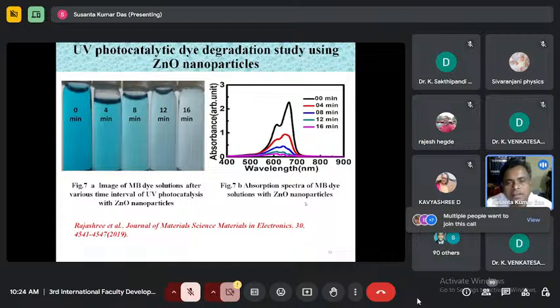Then we had gone for the results that we have shown here. You can see these are results of photocatalysis of MB dye. When we go for the experiment, we used to give the nanoparticle into the dye solution, and we used to stir at zero light or dark condition to have an adsorption desorption equilibrium. Then after that half an hour, we used to use centrifuge or a decantation method for separating the nanoparticles. Then after the nanoparticle gets separated, we collected the solution and went for UV visible spectrophotometer study, absorption spectral study.